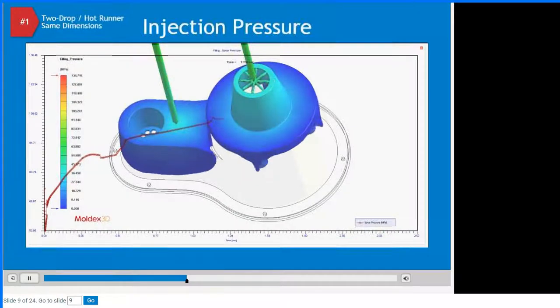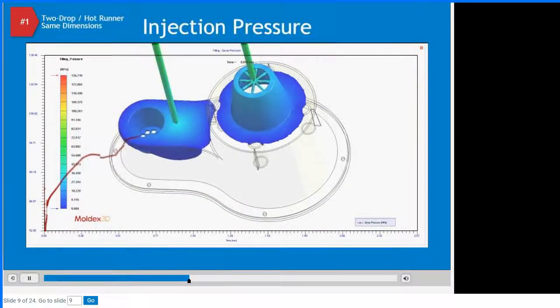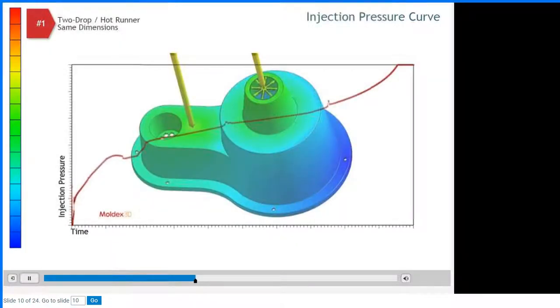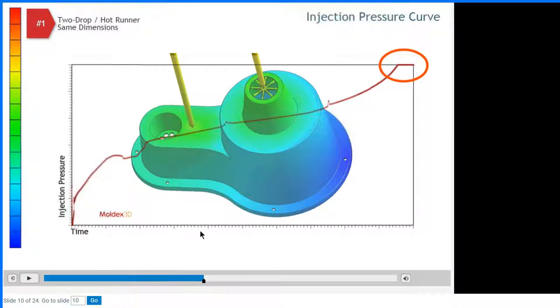Moving to the injection pressure during filling, the pressure graph for this first design shows that as soon as the smaller side fills, the pressure line indicates a bumpy increase until the switchover point is reached, at which the pressure becomes regulated. Not only does the material realign itself toward the unfilled side, but there is also a pressure accumulation on the smaller side — it is pressurized to a higher level than the larger side during filling. If you already have a pressure imbalance during filling, that is not good.